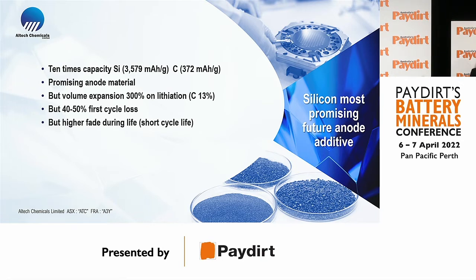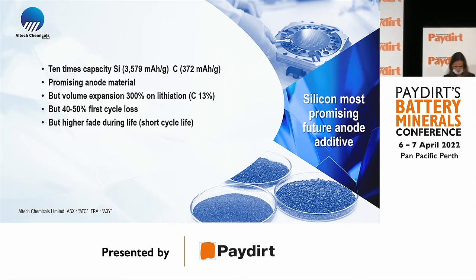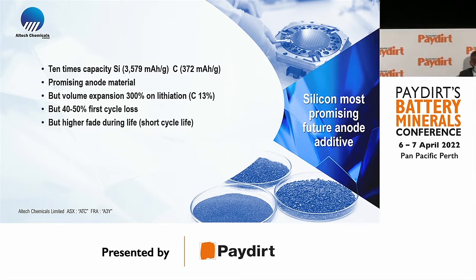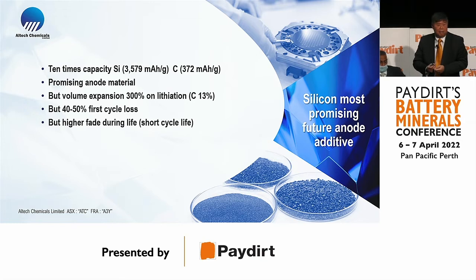There are essentially 3 problems. First one is that the silicon expands 300% in volume in lithiation and it fractures. Number 2, the first cycle loss. Like graphite, instead of 8 or 10%, it absorbs 50% of the lithium onto the surface and turns it inactive. That is a big problem. And the third one is the high fade. If you have less lithium ions, you're going to have less life of the battery.